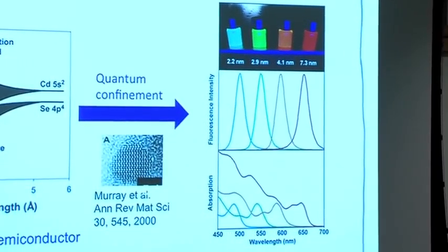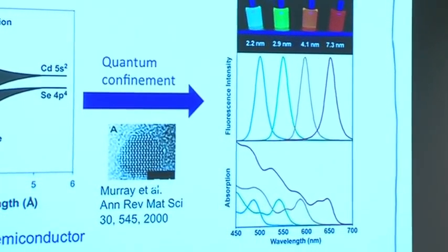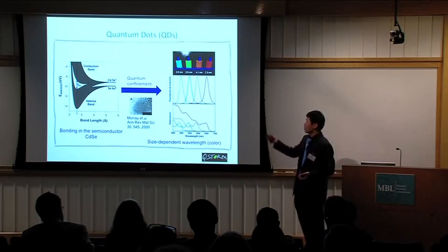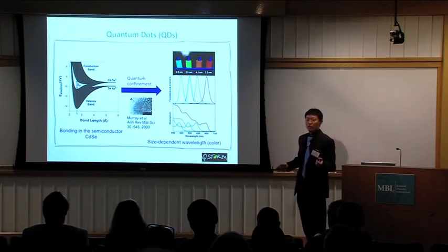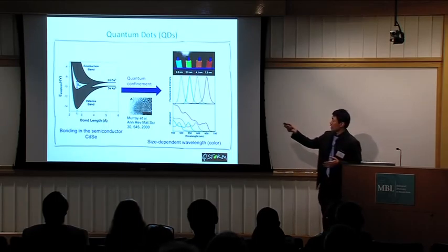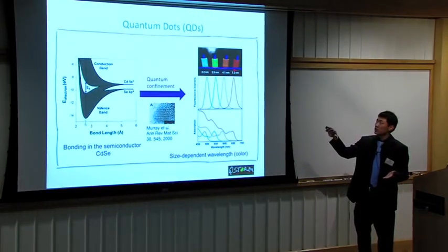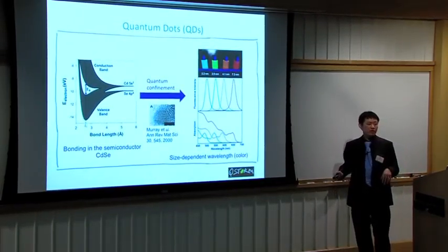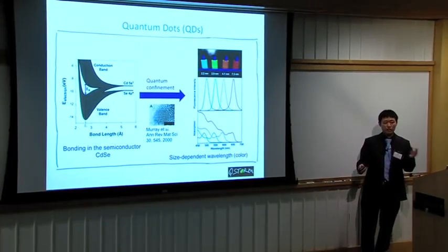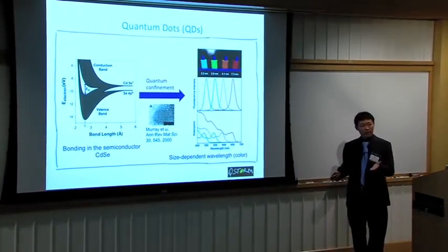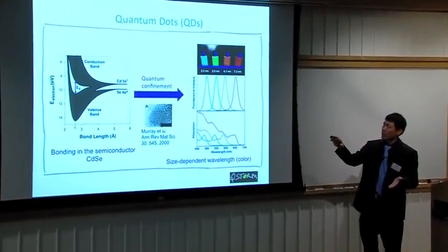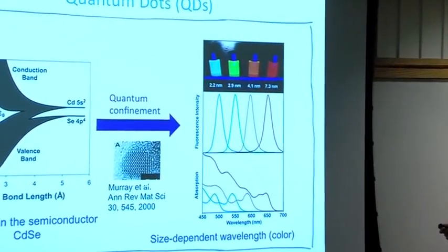When you make a semiconductor within nanometer size, we get the so-called quantum confinement effect and a lot of wonderful new optical properties. For example, we can use just one single illumination source to get different colors at the same time. The synthesis for these different colors of quantum dots is simply based on different size. We just change the reaction time of the synthesis chemistry, and we can get different sizes of quantum dots,